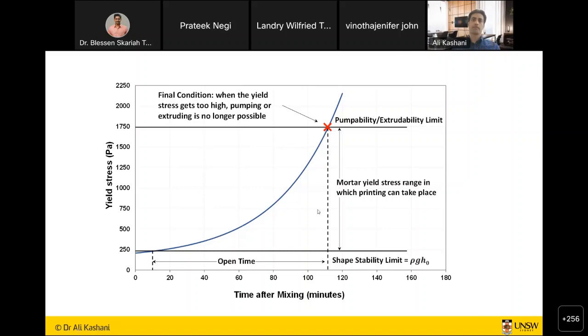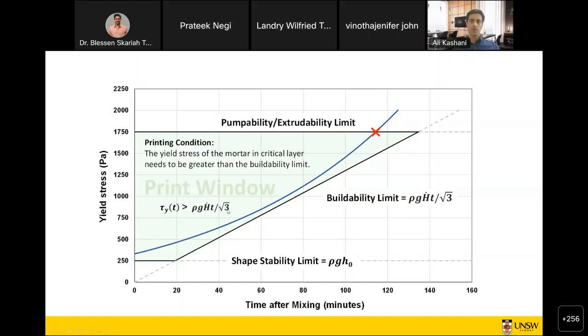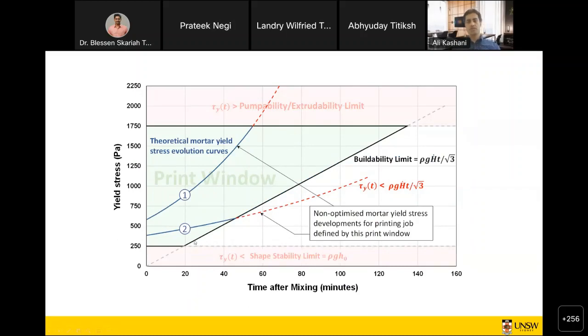So there is a limit that we can use the material in terms of the yield stress. And on top of that, there's a buildability limit. So it's just growing yield stress of the material in order to hold its self-weight without any collapse, plastic collapse, or elastic buckling. So we say the print window is based on these three boundaries of shape stability, buildability, and extrudability. And we want a material that doesn't cross these three boundaries.